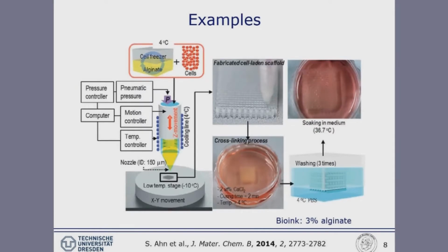Another example, looking more complicated than it finally is, makes use of this in situ cooling and freezing process. Whereas in the study shown on the slide before, everything was warmed up to physiological temperature, 37 degrees, here everything is done at low temperature. So the cells are mixed with an alginate hydrogel at 4 degrees Celsius. This is also the temperature of the reservoir of the syringe in which the cell suspension is stored. But then the printing process is done on the building platform, which is cooled down to a temperature of -10 degrees, leading, of course, to fast freezing of this aqueous alginate-based bioink. And this, of course, significantly stabilizes the structure.